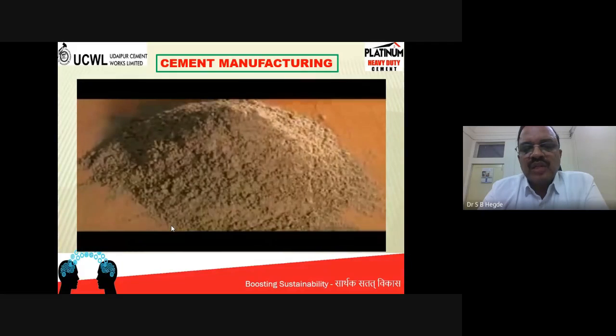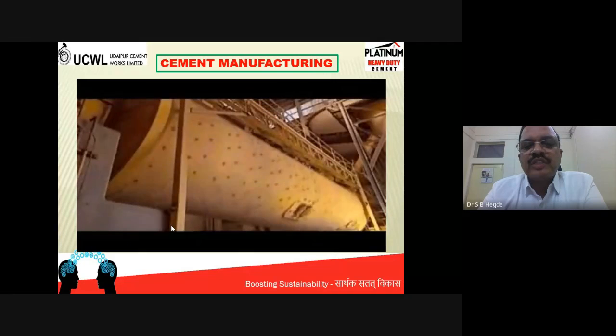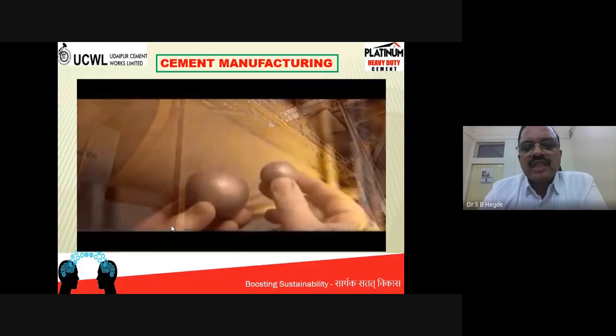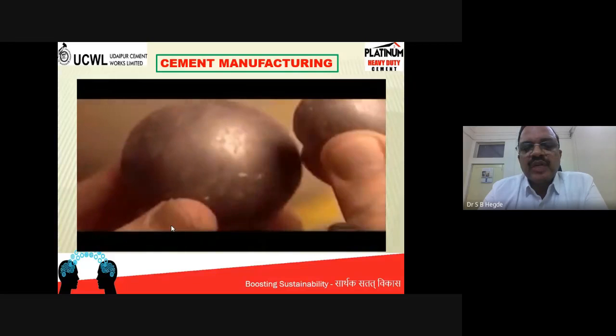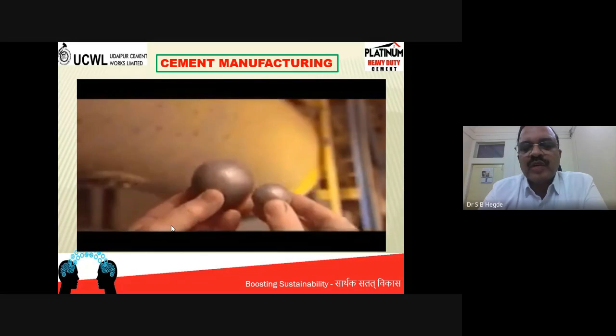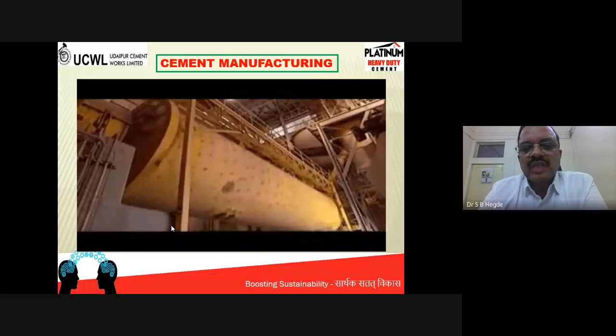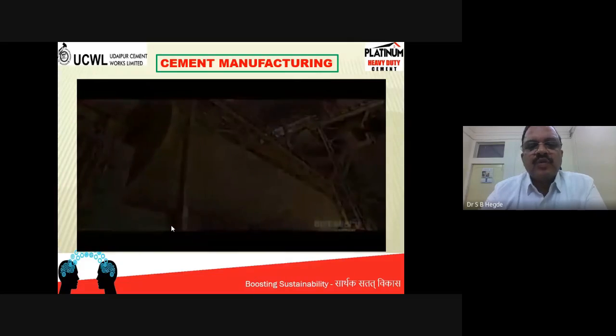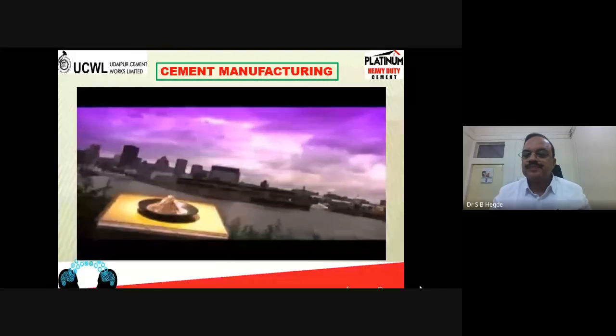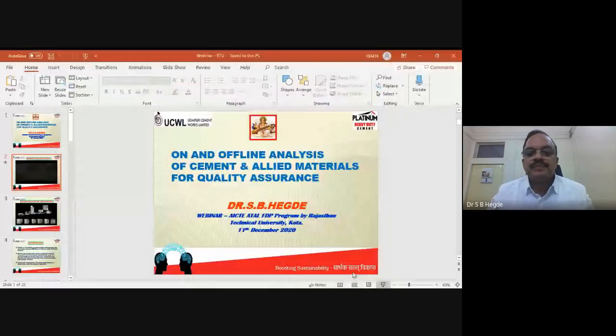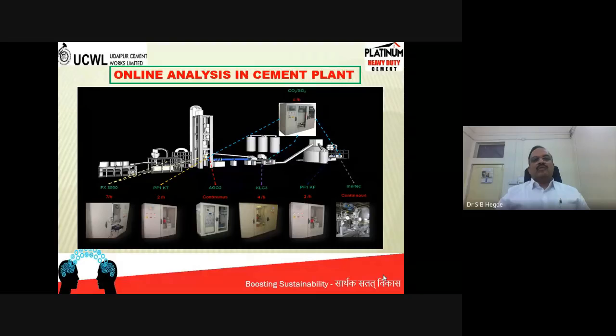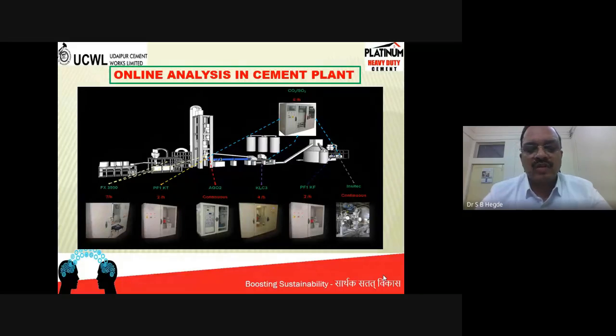Every 1 hour, the fineness of the ground material will be determined, as to whether it is as per the target or not. Inside the mill, you can see these balls. These balls bombard each other and the material, clinker and gypsum, and this forms a fine material called cement.